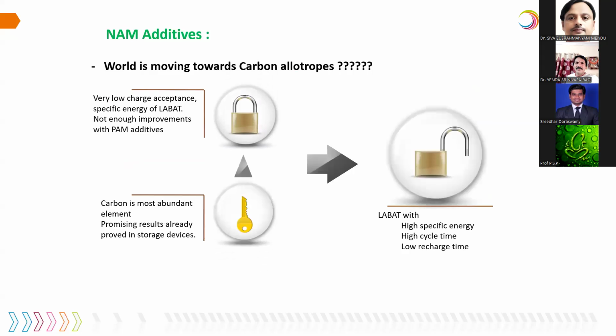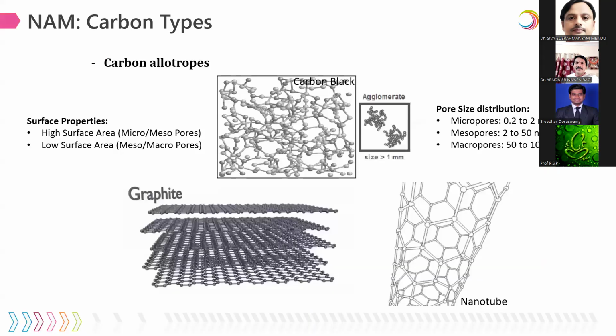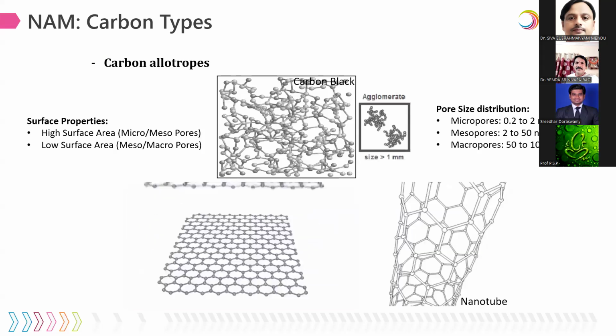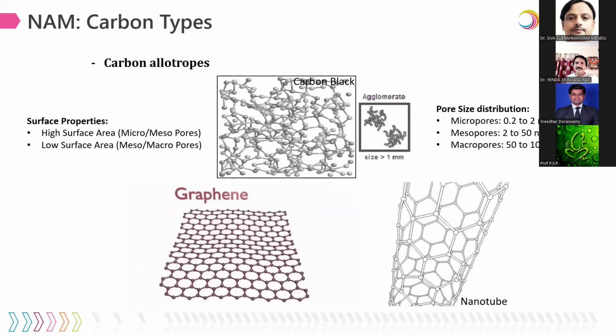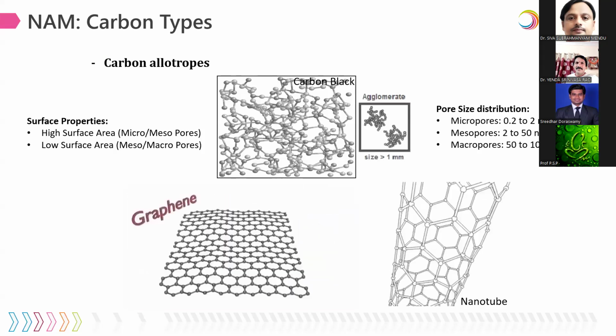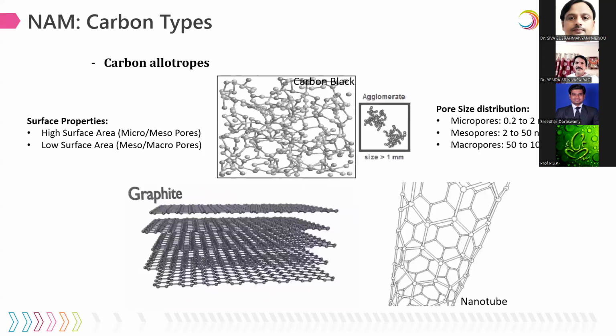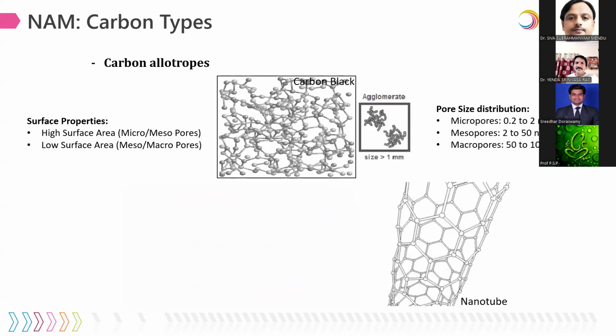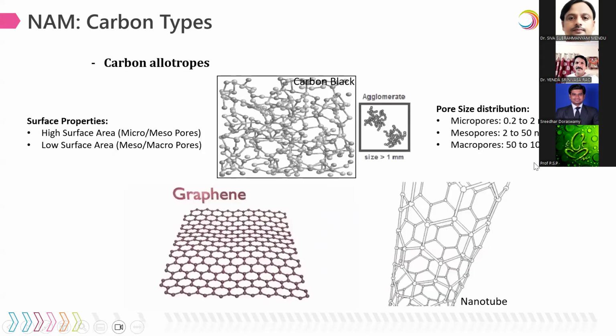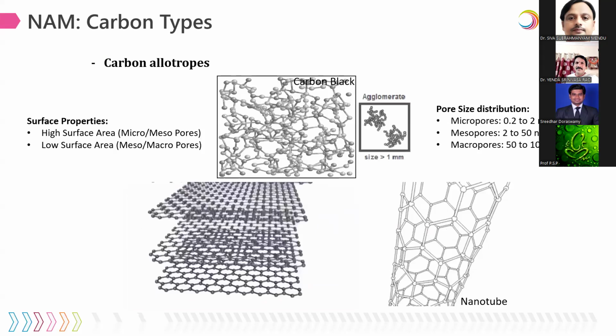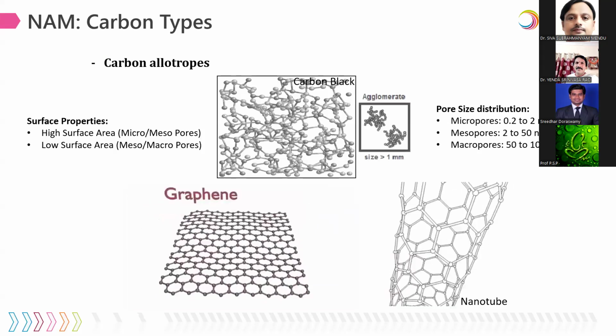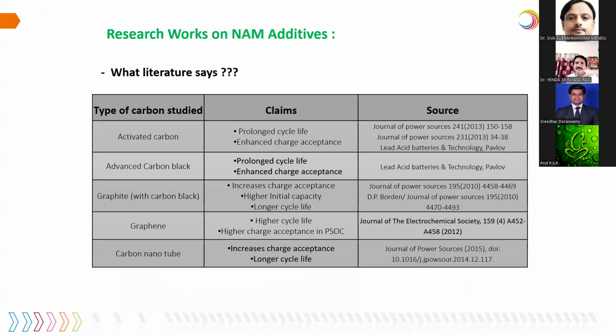Sodium salts, CMC, silica, and graphite have been used as PAM additives for improving the porosity. In the NAM additives, we use carbon black, barium sulfate, and lignin materials. Coming to carbon, it is a wide group of allotropes. I can classify them into basically two types based on surface properties, high surface area or low surface area, and also with respect to pore size distribution, micropores, mesoporous, or macroporous. We are using graphite type materials and nanotubes. Graphene is under exploration. A few competitors and active researchers are working on activated carbon, carbon blacks, graphite, graphene, nanotubes, etc.